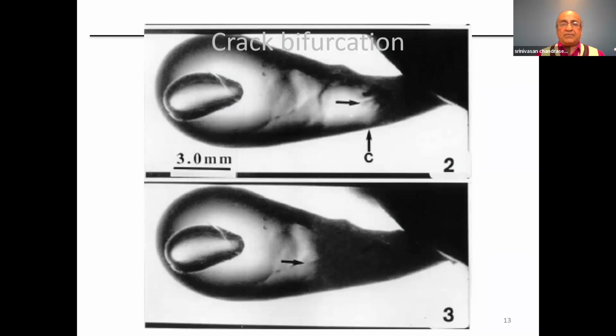If you look at this fracture front in greater detail, what we always found, at the arrow in the center of the core of the drop in the top picture, was what looked like fingers ahead of the crack front. The crack front is sort of curved, but they're always projecting fingers. These features were visible in practically every front that we imaged, and you can see that also in the bottom frame. So every crack front had finger-like projections protruding from the front.